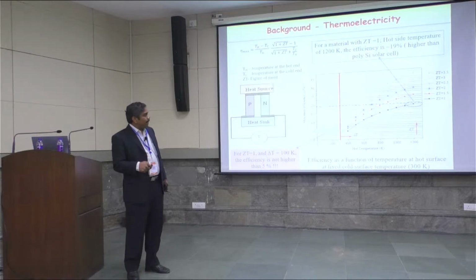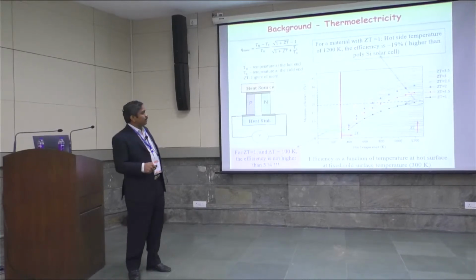Maybe I'll show some of the materials, but the one with silicon germanium can withstand more than 1000 Kelvin. The rest of them can be stable only below 1000 Kelvin. Because of that, you have to realize this high efficiency by tuning the figure of merit, which is a material-based parameter, and you can achieve the same efficiency even at about half of that temperature, around 600 Kelvin. But for that, your ZT should be more than 2. So you have to tune the ZT of the material, and how to tune the ZT of the material? Here, nanotechnology plays a role, and this is the strategy that people are trying to follow. Actually, the ZT is the ratio between the power factor and thermal conductivity. The power factor is nothing but the square of the Seebeck coefficient times the electrical conductivity.